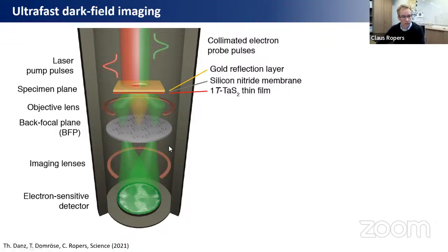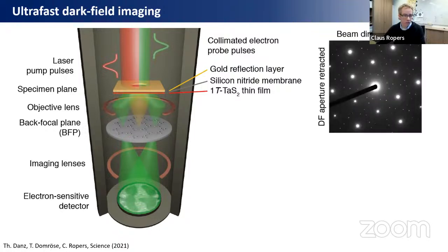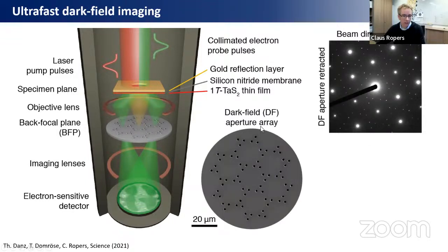And so here we developed a trick for this paper that allows us to emphasize and focus only on those diffraction peaks which are associated with the lattice distortion. As I mentioned earlier, we have the diffraction pattern, which we can record in the electron microscope, composed of strong and weak beams. Now, unfortunately, 90-some percent of the diffraction intensity is in these peaks, which don't tell you too much about this lattice distorted phase.